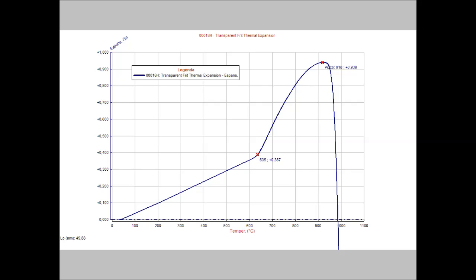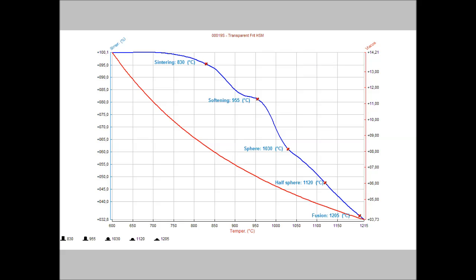One typical application is the quality control of the ceramic frits, where this information is technologically very important. Knowing the glass transition temperature, the temperature of dilatometric softening, and the half sphere point, it becomes possible to calculate the viscosity of the glass as a function of temperature, using the Vogel-Fulcher-Tammann equation, the well-known VFT equation.